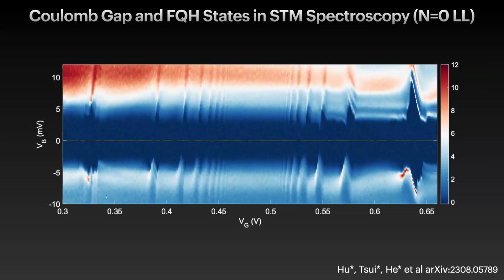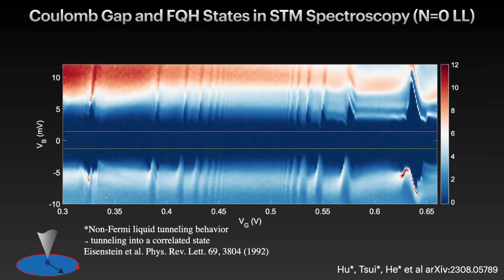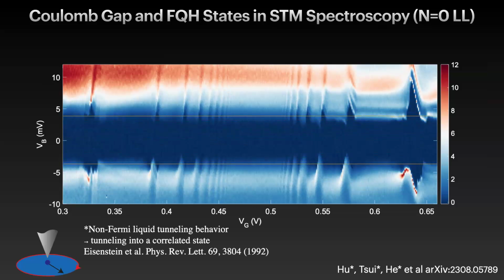This is the N=0 Landau level. And so you're tunneling near the chemical potential. What you see is this region which is dark. This is the Coulomb gap. So remember, we have a large magnetic field. So if you want to try to add an electron into the system, everybody's got to get out of the way. And this was discovered in gallium arsenide by Jim Eisenstein.